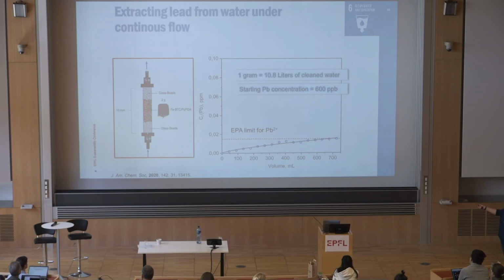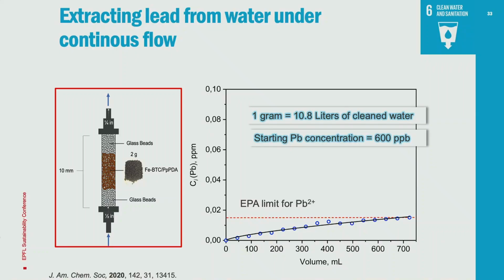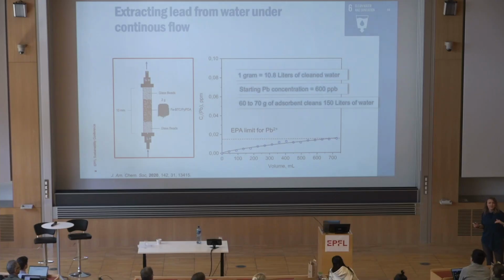What we find is that with 1 gram of material, we can purify on the order of 10.8 liters of water, which is pretty good. Just to give you an example, most home treatment units have 60 to 70 grams of material inside. They clean around 150 liters of water, and they're said not to work above 150 parts per billion. Our experiment was done at 4 times that concentration. So we're quite happy with these results.